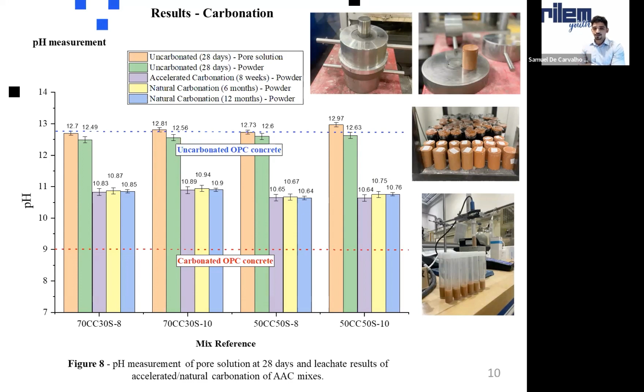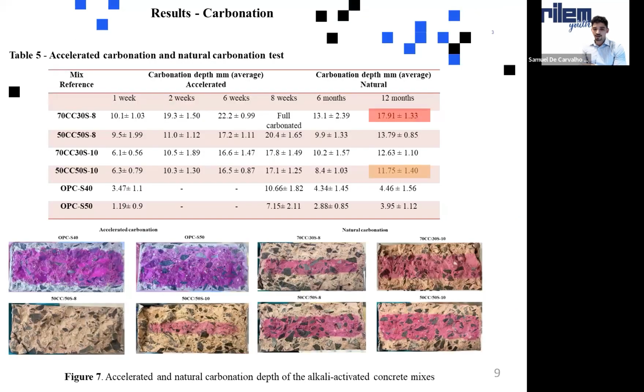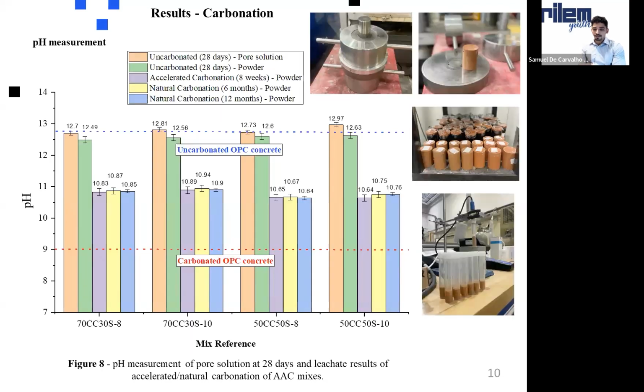A really interesting thing that you noted before is that the phenolphthalein experiment that we showed before is pretty much calibrated for normal OPC. So as you guys see here, the OPC, this white area, is truly carbonated. The pH of this area is something around 9.